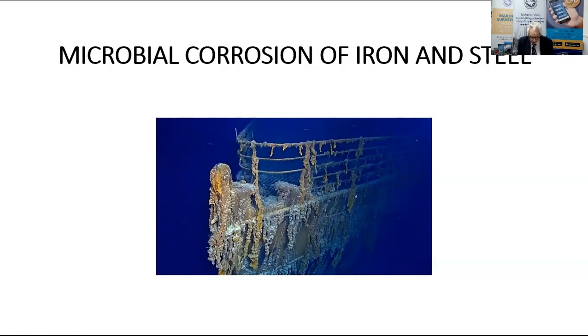The bacteria can be broadly classed as aerobic, i.e. those requiring oxygen to become active, or anaerobic, those not requiring oxygen, as the gas is toxic to the bacterium. Sulfate-reducing bacteria, or SRB, are anaerobic and are responsible for most incidents of accelerated corrosion damage to ships and offshore steel structures. They are also responsible for much of the damage to the bottom plates of canal boats, a region where, in accordance with Henry's law, free oxygen is in relatively short supply. Iron and manganese oxidizing bacteria are aerobic and are frequently associated with accelerated pitting attacks on carbon steel plating and stainless steel at welds.